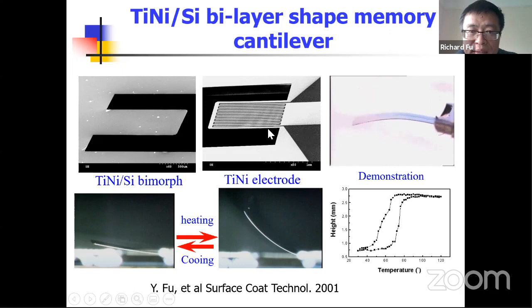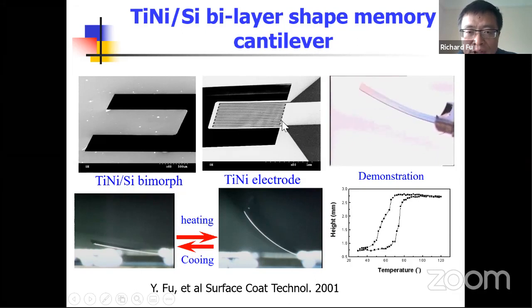The shape memory effect will change the shape of the material. Once you stop the electric current, there will be a phase transformation back to martensite. Then the material will return back because the silicon will bend it back. So that means with a very small, low temperature change, we have a large, significant change of the shape of the cantilever. So this is the bimorph or bilayer design structure.